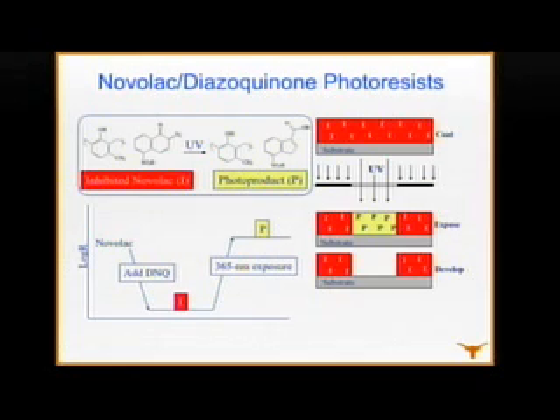Now if you shine light on this film, this substance is converted by a series of well-known reactions. First it forms a ketene through the so-called Wolff rearrangement, and then the ketene adds water to form a carboxylic acid. So I've switched this lipophilic material to a very hydrophilic, even acidic material, and therefore the film dissolves again very rapidly. So I take a material that's insoluble in base, shine light on it, selectively convert a region into an area that dissolves quickly, then immerse the film in base. This part dissolves out, this is left behind, and I can now transfer this pattern into the substrate and either etch away material or deposit material, and use that to build up the layers of semiconductor, conductor, insulator that are used to produce the device.